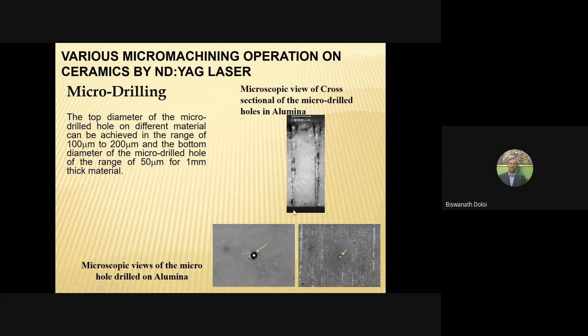This type of hole you can produce: a taper hole. Obviously this is a drawback for laser beam machining, although you can focus it at different levels to make a straight hole. But if you consider the fixed focusing condition, then a taper hole is observed. Here the top hole size is 100 micron, bottom is 50 micron, and thickness is 1 millimeter.